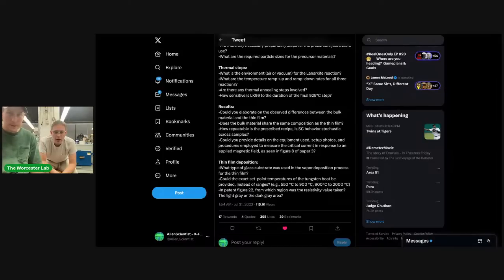But in any case, how repeatable is the prescribed recipe? Well, it's stochastic. That's because the ingot that they're making isn't just the superconducting phase. There are other phases in there, and if your copper doesn't diffuse properly into the rest, then you're not getting the right phase throughout with the right dopants.